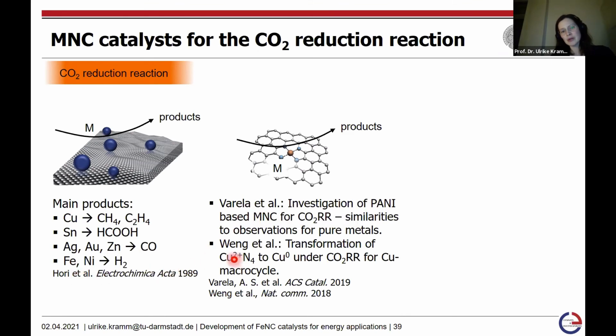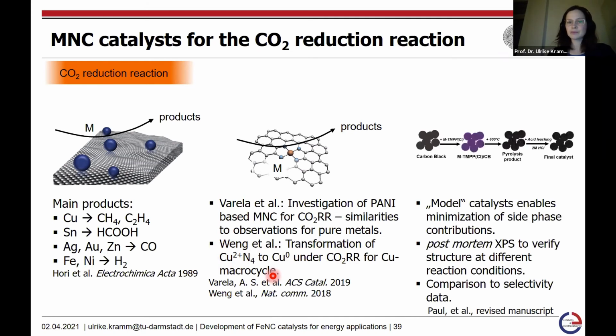But what is also interesting was another work by Weng, who showed that there was a transformation of the Cu-N4 centers to the metallic state under the reaction conditions for a Cu macrocycle. And there was again also a work in relation to a Cu-N-C catalyst, but again with the drawback that the preparation strategy might have led also to some side products based on the pyrolysis temperature and so on.